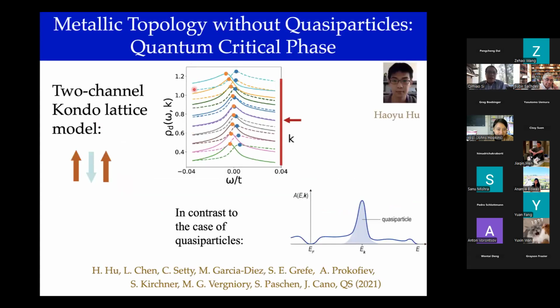The first thing we did was that if we can study single channel Kondo effect, which is what I described, we could also study a multi-channel Kondo effect and put them in some interesting lattice. Multi-channel Kondo effect has local moment coupled not just to one species of conduction electrons, but in fact two degenerate species of conduction electrons. So the local moment spin wants to form a singlet with this species of conduction electrons, and at the same time it wants to form a spin singlet with this species of conduction electrons through the antiferromagnetic Kondo coupling. The two things cannot happen simultaneously, so this frustrated situation in the two-channel case leads to non-Fermi liquid, as would be, say, the three-channel and the multi-channel case.